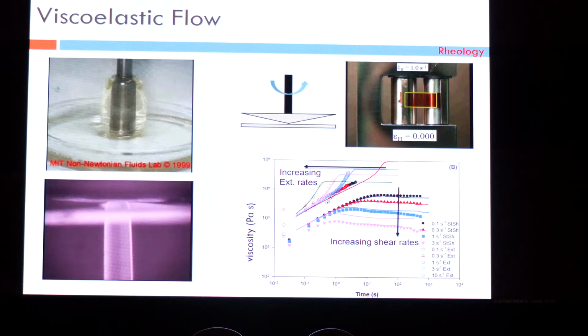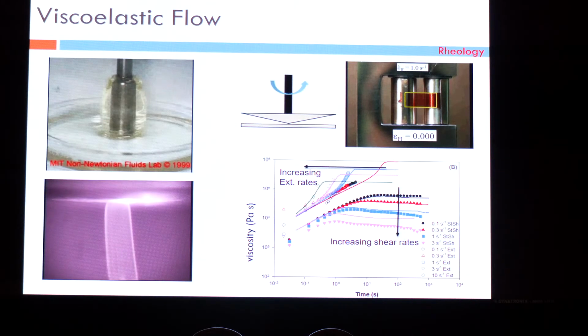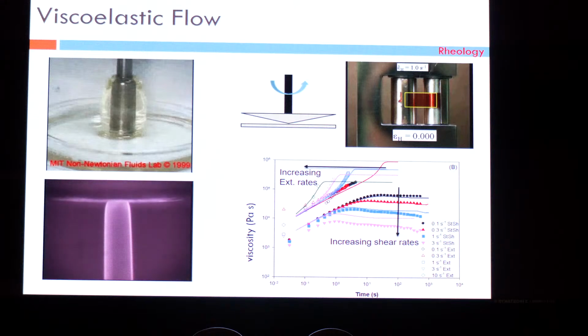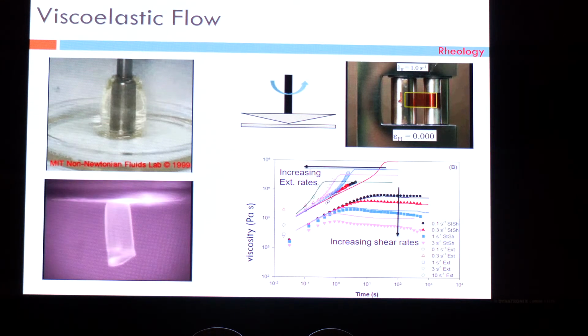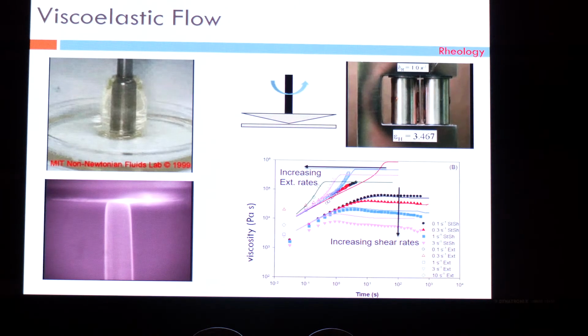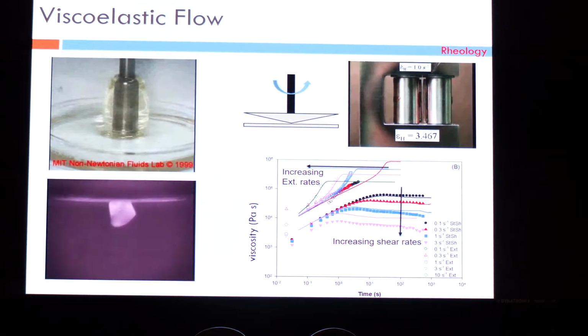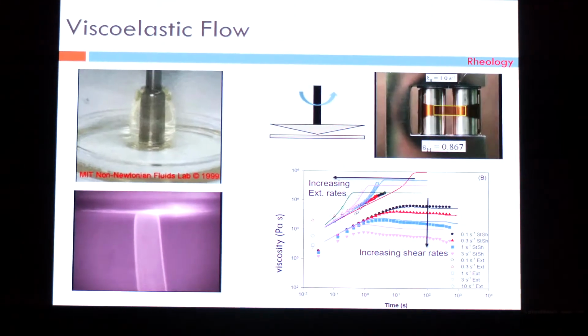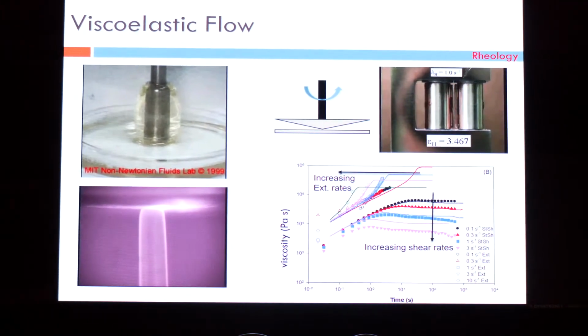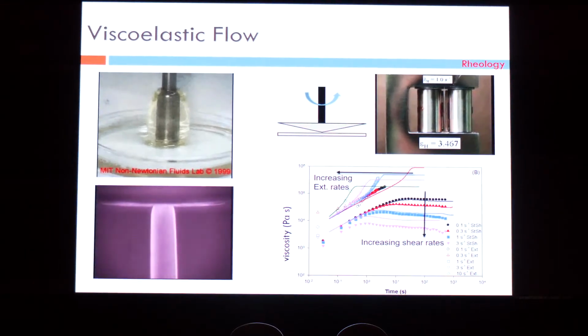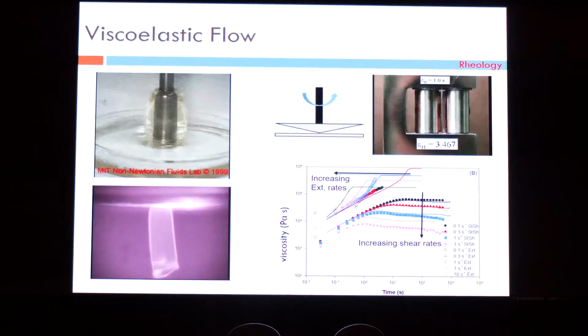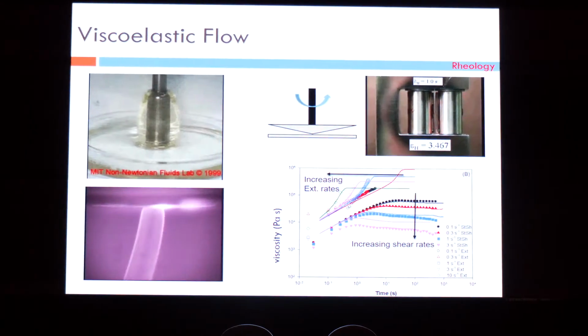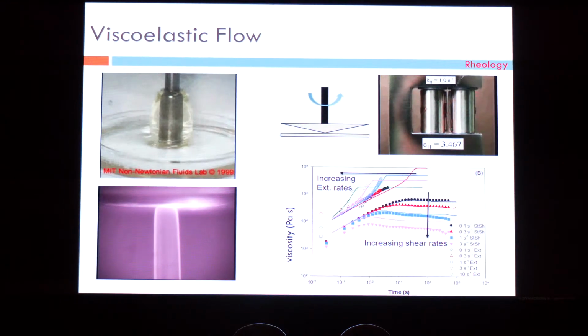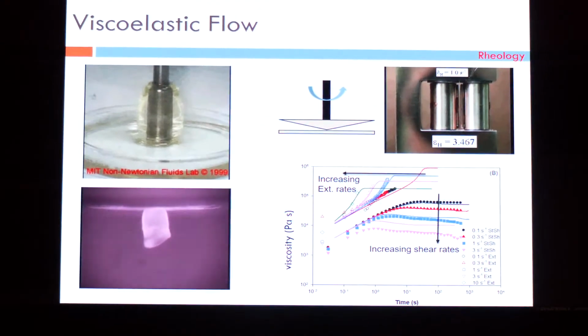On the right, you see two drums, and if I can play that video, there's a small video there. You will see this yellow squared box, which is sort of held between the two drums, and as the drums rotate, this film of material is stretched. You think it is a solid piece of material. It's not. It's actually a molten polymer mass. That film that you see is a polymer liquid. It's a melt. You heat it above the melting point of the polymer, and you can stretch that polymer film. These are not properties that you normally see for usual liquids like water or an oil. These are very unusual flow properties of these materials.